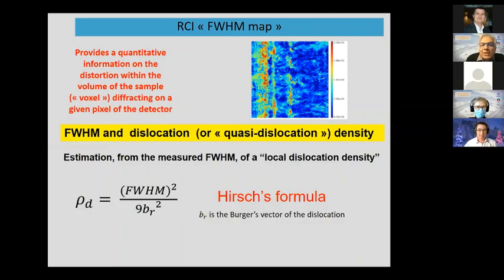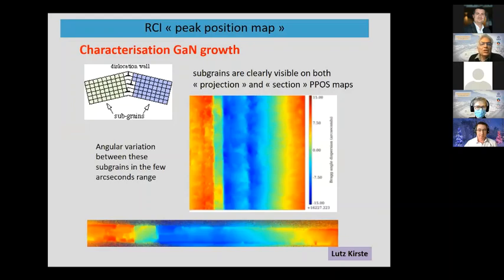The full width half maximum map is very interesting because it provides quantitative information on the distortion within the volume of the sample diffracting on a given pixel of the detector. For instance, if you want to have the density of dislocations, if you see the dislocations, you can count them. But even if you don't see them because they are superimposed one onto the others, there are very simple formulas, the Hirsch formula, which from the full width half maximum and the Burgers vector of the dislocations gives you the local dislocation density. So you can estimate from the full width half maximum map your local density, even if you don't see the dislocations individually. The peak position map characterizes other aspects.